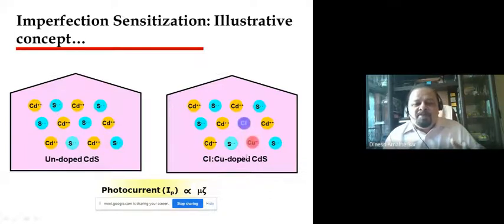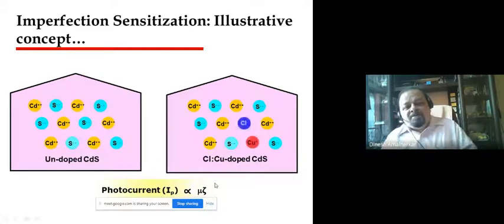So let me repeat here. This leaves an interesting situation. Cu+ in comparison to Cd+2 has effective negative charge, which exerts Coulombic repulsion towards photoexcited electrons in the conduction band of cadmium sulfide, ultimately leading to enhancing tau. Since lifetime increases, photocurrent also increases. That is the theory of activating pure cadmium sulfide, highly pure 99.9999% cadmium sulfide, with chlorine and copper.